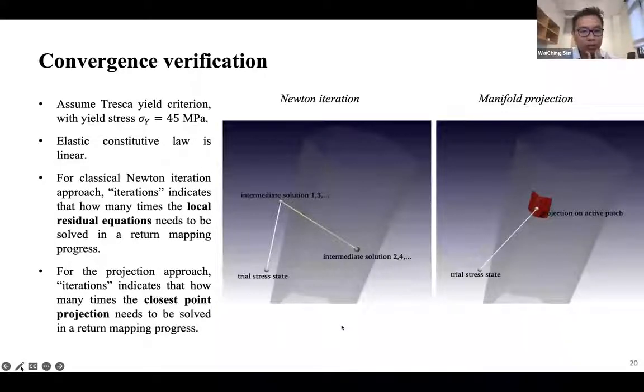This is one example of a perfect plasticity Tresca yield surface. We want to try the return mapping algorithm with the classical Newton-Raphson algorithm directly on a point that is just a little bit outside of the yield surface. Not surprisingly, if I try solving it with the standard Newton-Raphson algorithm, the two intermediate solutions just keep iterating. This is due to the fact that the two stress gradients can lead the Newton-Raphson residual to just go back and forth between the two patches.